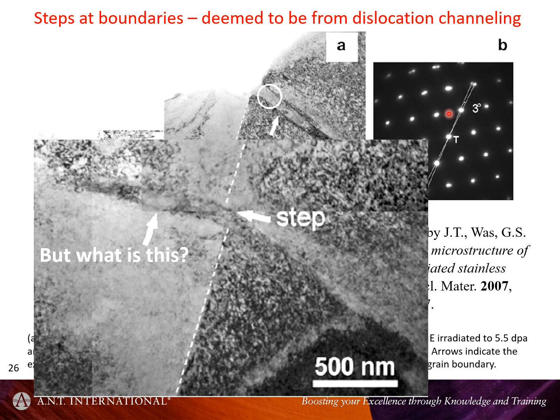The only other way is to have some constraints, but if you've got a foil, you've relaxed the constraints, it's very difficult to envisage that could be real. But you've got this peculiar structure here, which could indicate subgrain boundaries, I don't know, that in this odd shape, you could have had a different phase here, which has since disappeared. I really don't know. But channel, I'm not sure.